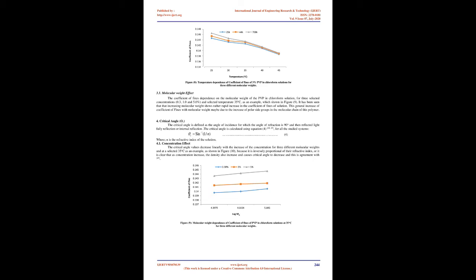1.3 Molecular weight effect. The refractive index dependence on the molecular weight of PVP in chloroform, for 3 selected concentrations, 0.3, 2.0, and 5.0%, and temperature 35°C as an example, is demonstrated in figure 3. It can be seen that the increase of molecular weight causes a rather rapid increase in the refractive index of these solutions. This general increase of refractive index with molecular weight may be due to the increase of polar side groups in the molecular chain of the polymer [27].